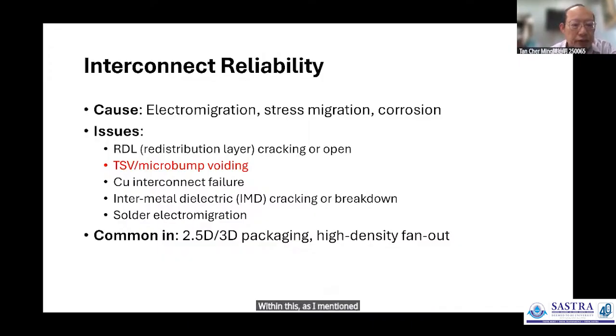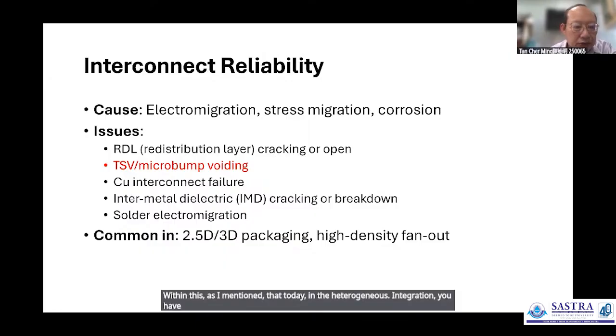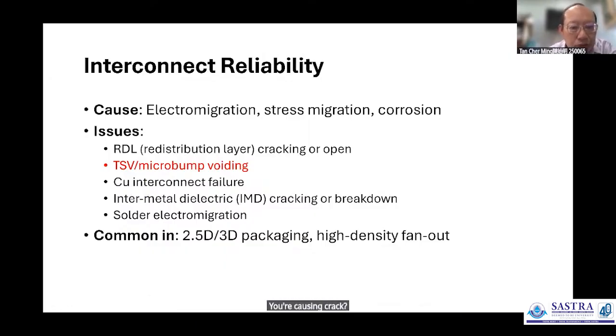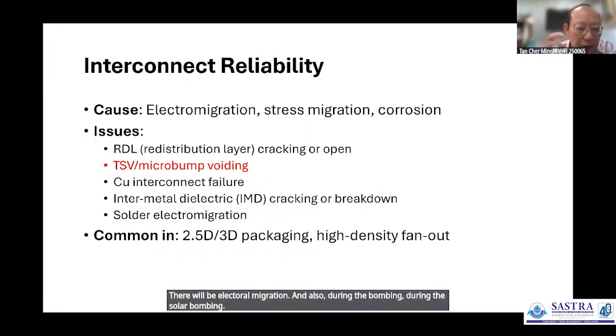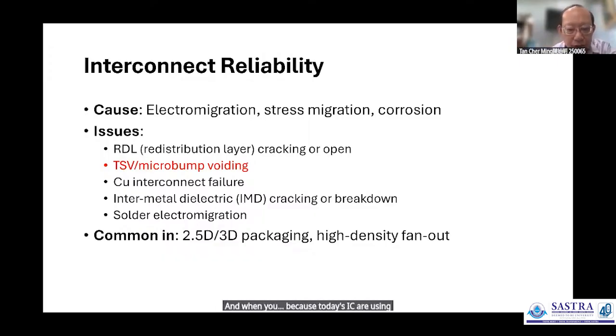Within this, as I mentioned, today in the heterogeneous integration, you have the RDL, which stands for redistribution layer. You're causing crack because of the stress migration. The TSV, just like I mentioned about the 3D IC and the microbump, can have void and therefore causing open circuit. The copper interconnect in the tiny PCB inside the chip itself, because the line width of the copper will be still very small, unlike the traditional PCB, there will be electromigration. And also during the solder bonding, because today's IC are using an ultra low K, when you try to solder the solder bump into the RDL itself, the mechanical force can cause a crack in the underlying dielectric. And solder, of course, itself is so tiny that solder electromigration is a problem.